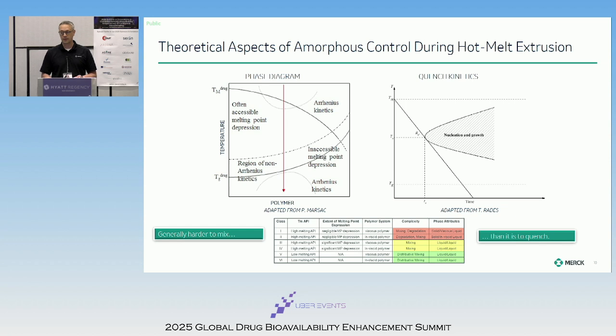formulation that we're developing. Essentially, the more melting point depression that you see, or the lower melting temperature that you have, generally the easier it's going to be to leverage hot melt extrusion. Similarly, the lower the viscosity, the easier it's going to be to create a single phase system. And so these allow us to make some early assessments around viability of the platform.